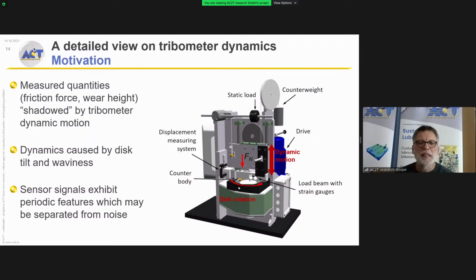But this is a mechanically seemingly very simple machine, yeah, but it is not as simple as it might seem, because the disk is never completely flat, and it is probably not even possible to mount it in such a way that the surface is completely normal to the rotation axis. Yeah, so it has a certain tilt and it has a certain waviness. And if this disk spins fast enough, it will give rise to some dynamic excitation of the system. And if you are unlucky, you will run into one of the eigenmodes or the eigenfrequencies of this system, and it will behave in a way which will basically shadow your actual measurement data.